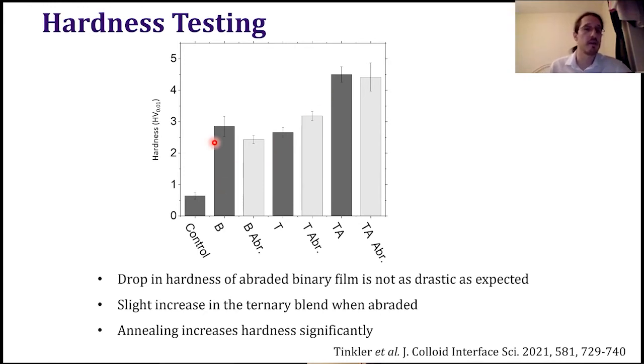So you can see that from the binary blend and the abraded binary blend, there's not much of a drop in hardness. And for the ternary, there seems to be an increase. But what we can clearly see is that when you anneal this coating, the hardness increases significantly, which is expected because you have latex particles which are going to interdiffuse and have a better coalescence after annealing. So we were happy that this was another application that seems very promising.